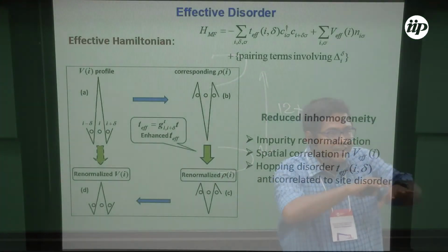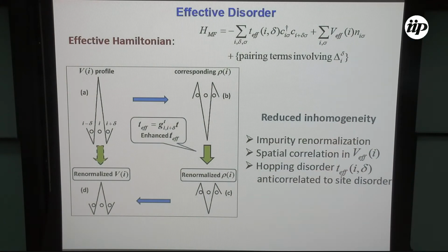So there are three processes by which the system reduces the inhomogeneity. First, it screens the disorder because of the Coulomb repulsion. It introduces a bond disorder because earlier T was just a constant everywhere. Now T depends locally on the local disorder potential. And also, interestingly, these two go anti-correlated with each other. That means the places where T would be high, V would be low, so they compete with each other, making the system far more homogeneous.